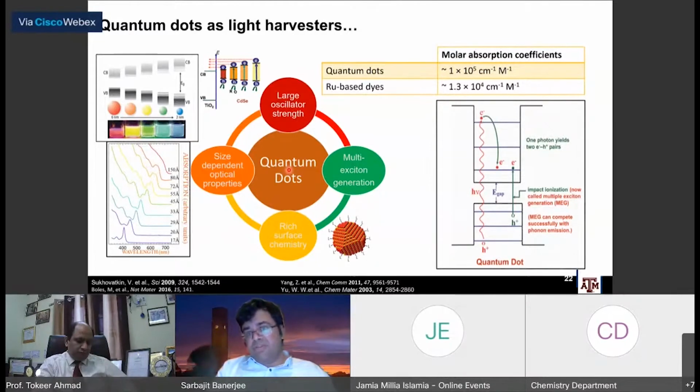So quantum dots have been great in solar cells. Both chalcogenide quantum dots, as well as especially perovskite halide quantum dots, but there's a major problem that we have to deal with if we want to use them in conventional photocatalysis, and that's the fact that they degrade in the water, right? So if you're going to use these to generate hydrogen and oxygen, they tend to be extremely unstable. And for quantum dots, the reason they're unstable is because they undergo photocorrosion, right? So they absorb light and then they photocorrode, and then they fall apart. So one of the biggest challenges that I'll tell you about solving is how do you prevent photocorrosion of the quantum dots, okay?